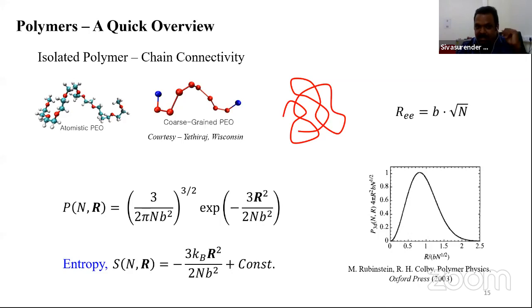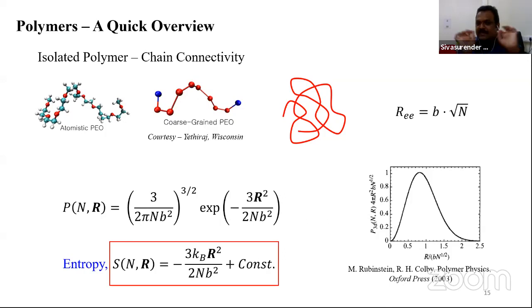which is just the probability times the logarithm of the same probability, summed over all the microstates. And now if you look at this entropy closely, entropy is essentially defined by the end-to-end distance of the polymer. If you change the end-to-end distance of the polymer, the entropy of the system will change. At equilibrium, the system wants to have maximum entropy, and the moment you start changing the length, the entropy changes and the system goes out of equilibrium, right? So with this basic idea, let me introduce you to a very simple experiment, right?